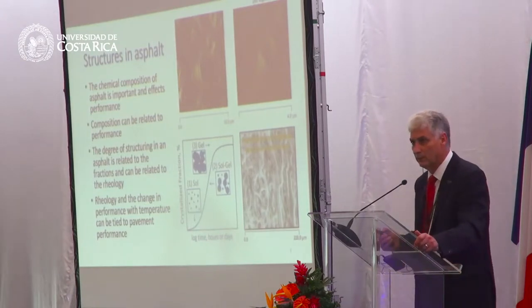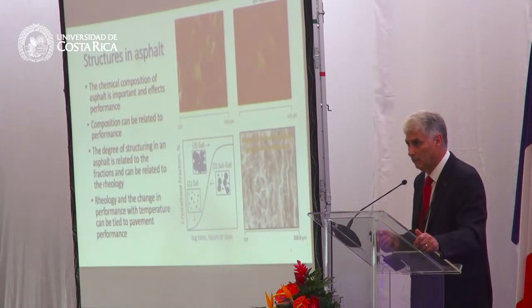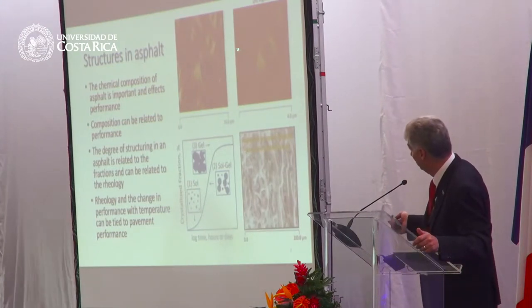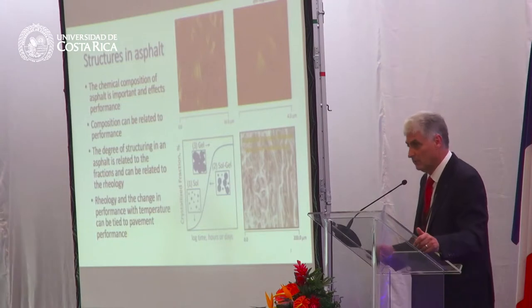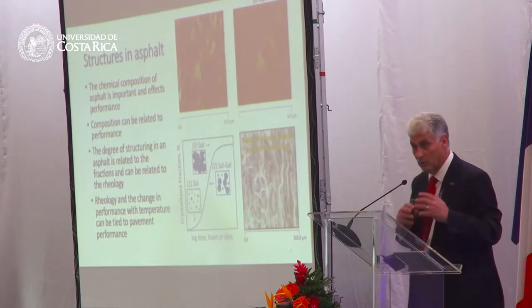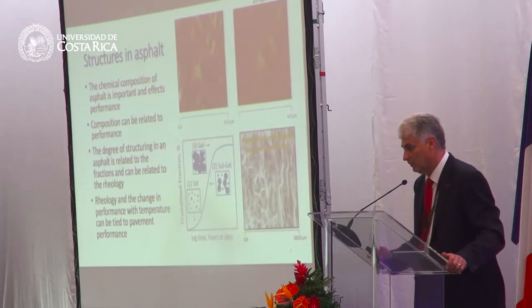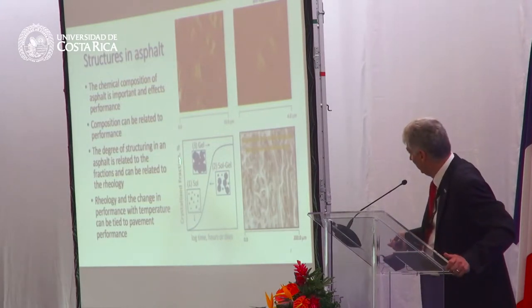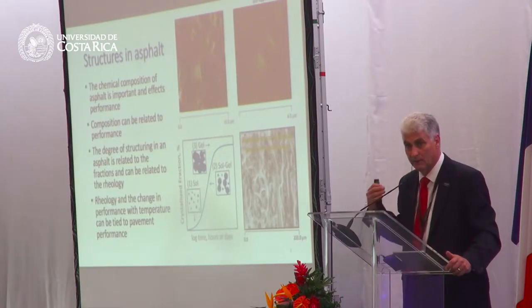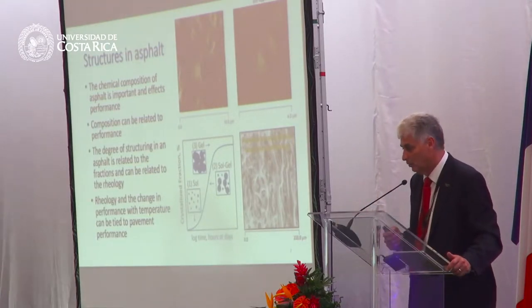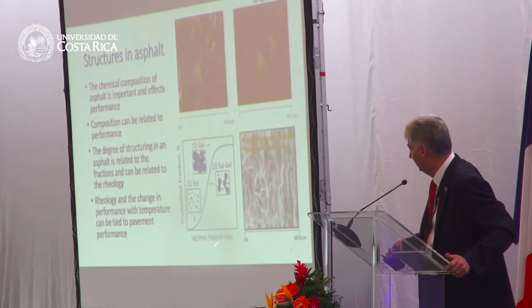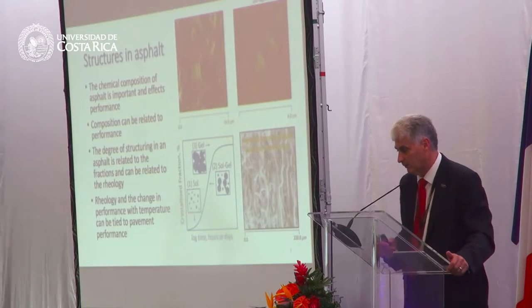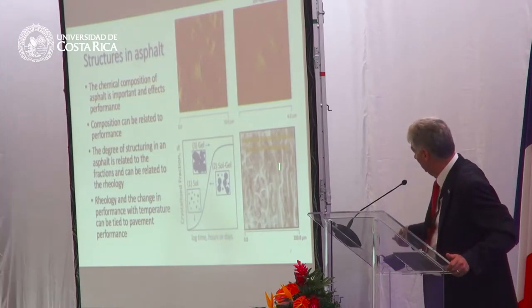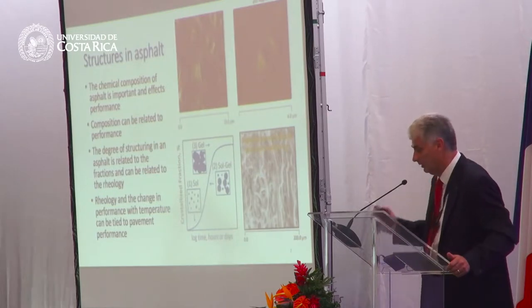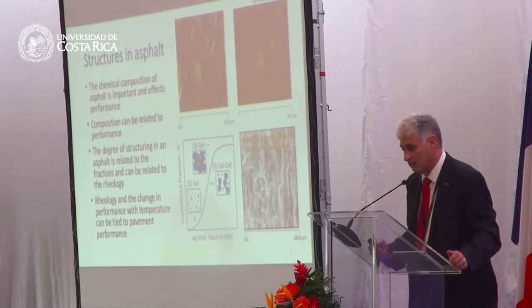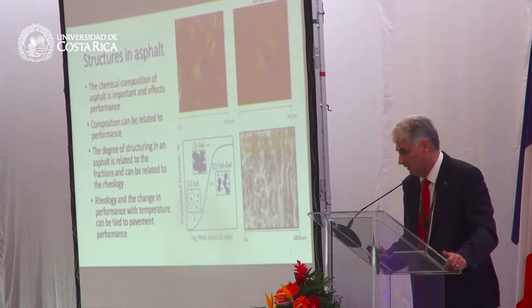These photographs I took out of a recent AAPT paper in March this year, and they were showing some of the structures that you see in asphalt. Some folks have commented on these bee-like structures you see when you zoom in on the asphalt fractions. The older way of looking at asphalt fractions might be to look at an asphalt binder behaving like a sol material, going to a gel-type structure. As the asphalt ages, you see the fractions in the asphalt changing. The slide here shows some structures, asphaltenes and resins, in an asphalt structure under a scanning microscope.